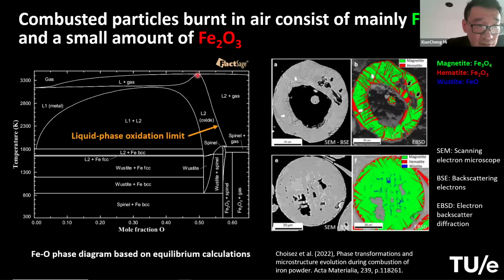And this boundary over here is basically the liquid phase oxidation limit, because beyond it, liquid iron oxide cannot take any more oxygen from the gas into it, right? That means if you are burning this iron particle very rapidly in liquid phase, it should reach this boundary. And what does this boundary correspond to in terms of stoichiometry? You need to lower it and look at here.